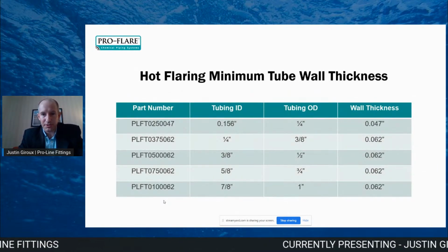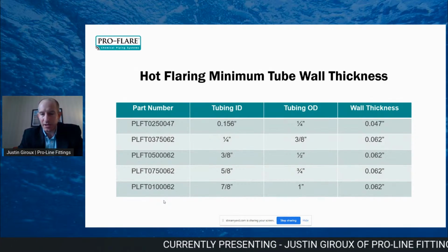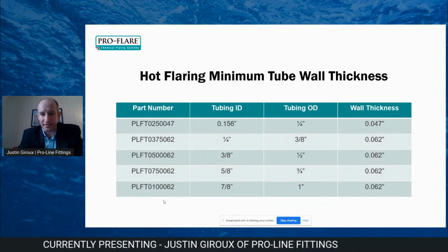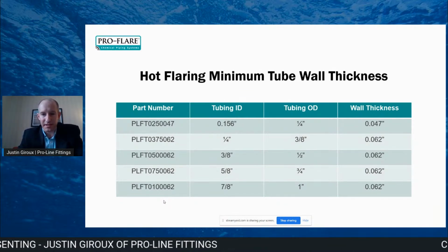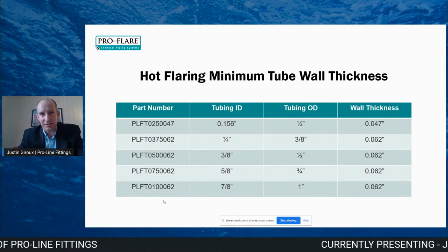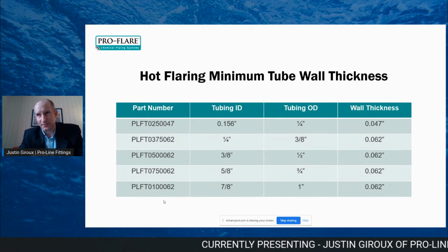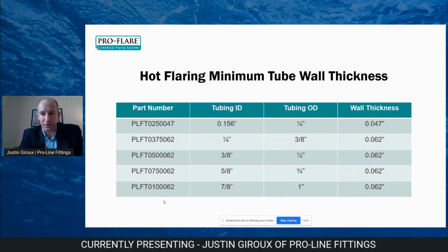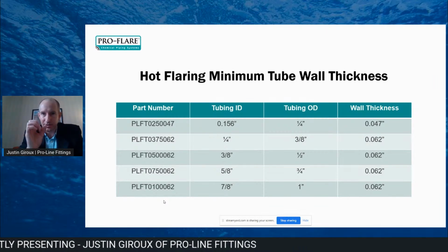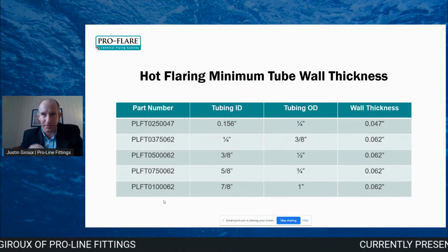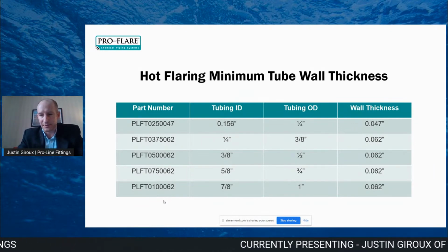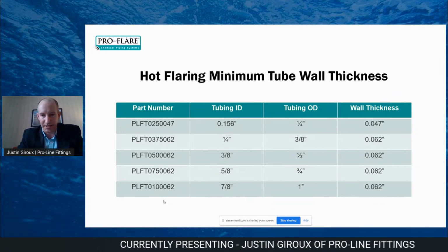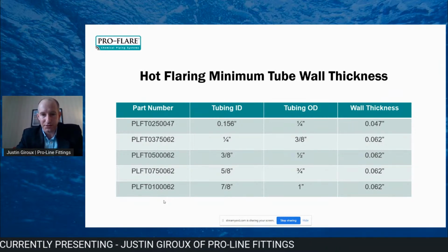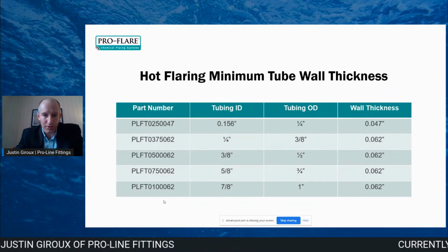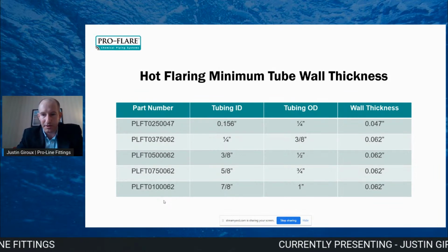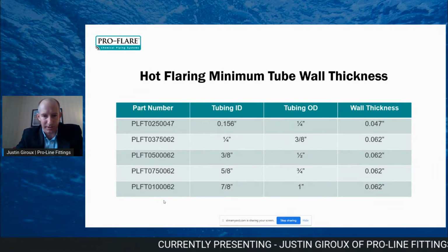So there are some minimum tube wall thicknesses you have to pay attention to. We learned the hard way that 0.062 wall thickness at 1/4 inch is too thick. It's doable, but very difficult to flare 0.062 wall thickness at 1/4 inch. It's essentially the ratio of diameter to wall thickness is such that when you heat it up, the flare end kind of breaks down on you, and you end up with a kink. Doesn't look right. So at 1/4 inch, 0.047 tube wall thickness is what you want. And then beyond that, from 3/8 to 1 inch, you want to use 0.062 inch wall thickness.